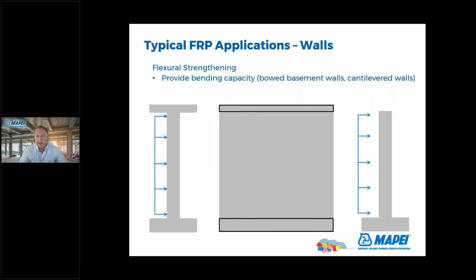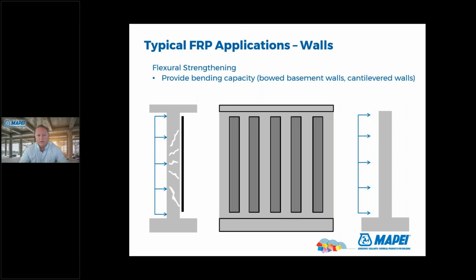So another common application, this is for walls. If you want to do some flexural strengthening on a wall, say this one on the left, you have a load, and on the right side of that wall, it's going to be in tension. So you put the FRP there, and you can do this in strips. We see this a lot with inside basements that are bowing from the outside soil. They'll go and they'll put these FRP up against the walls. You're not adding anything. You're not losing any space in your garage by doing this.